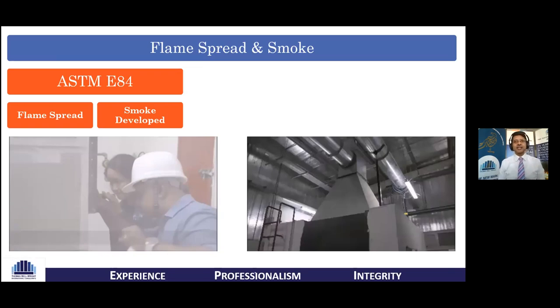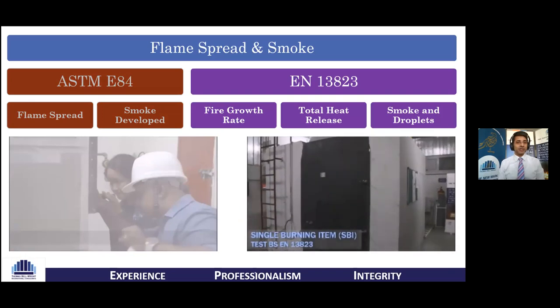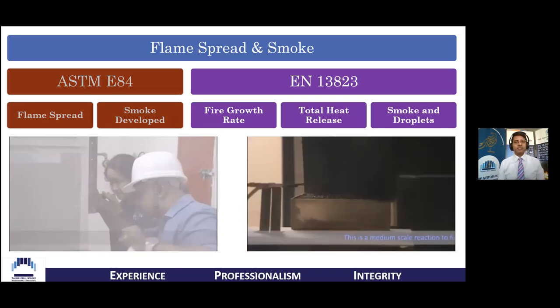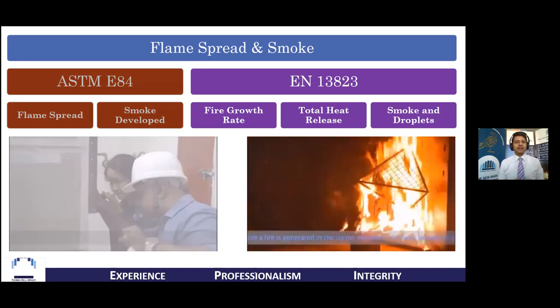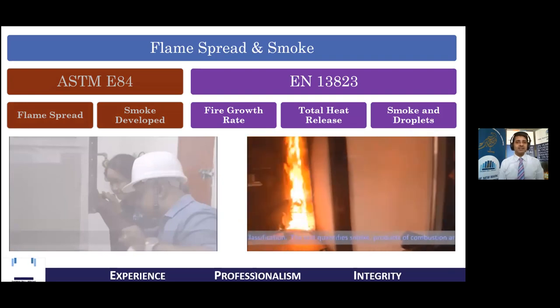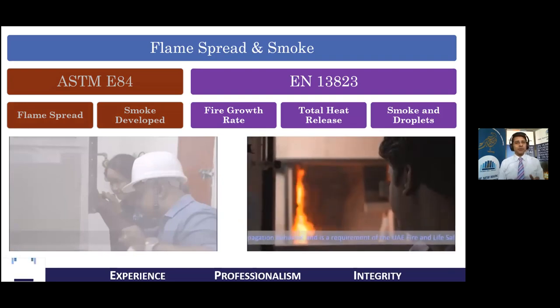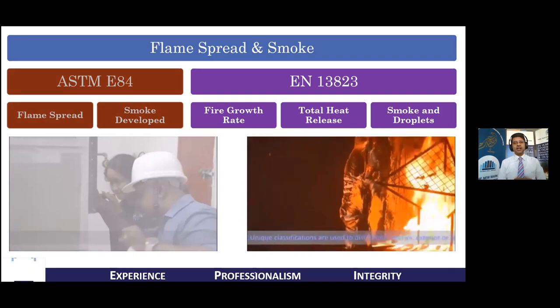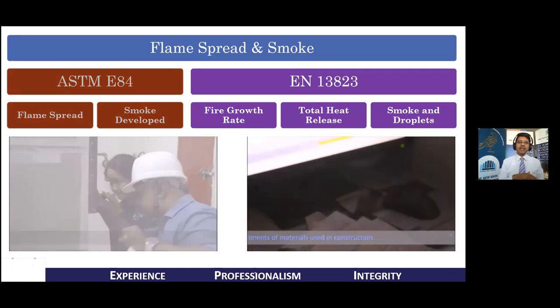The ASTM E84 test, as an example, as well as the European norm EN 13823, which is much more detailed in arriving at the fire growth rate, the total heat release, the smoke and droplets behavior. Both these tests arrive at trying to quantify how much flame gets spread over the surface of the material. These tests are often used to define and create limits of building materials that can be used in finishing or in such areas of the building which can possibly carry a fire to a distance.